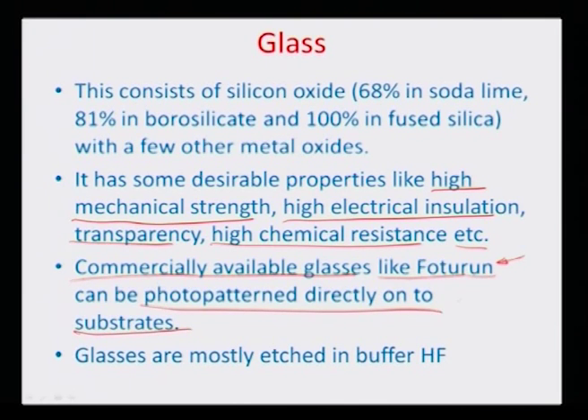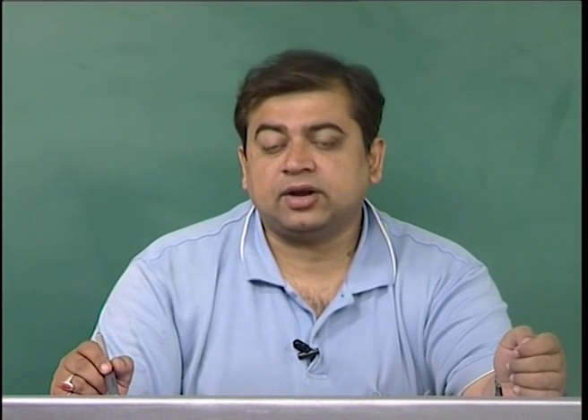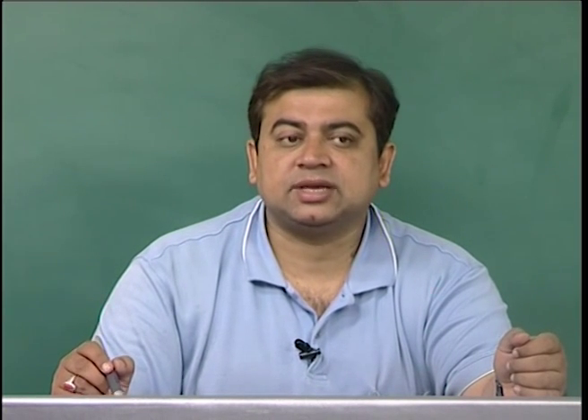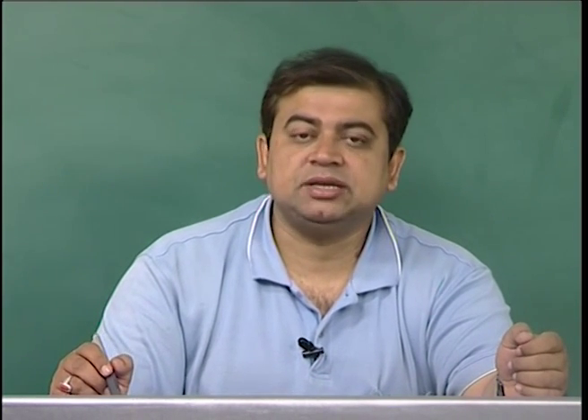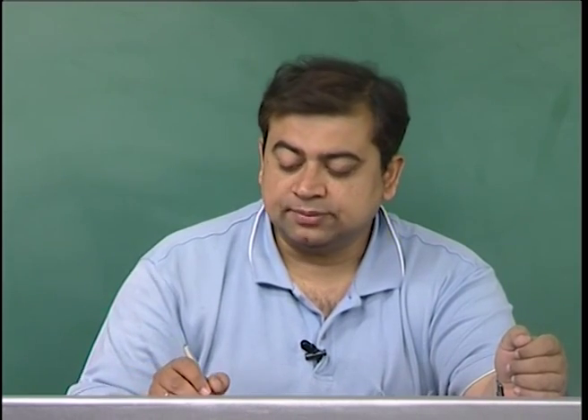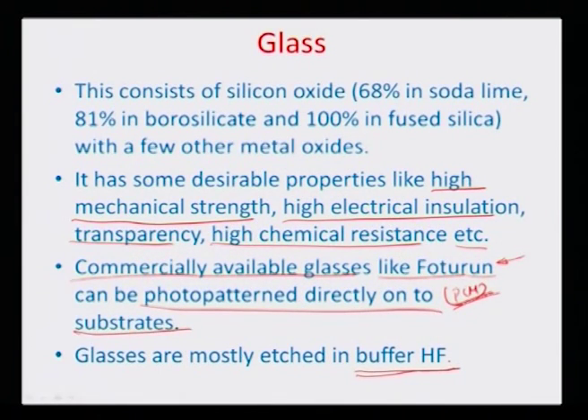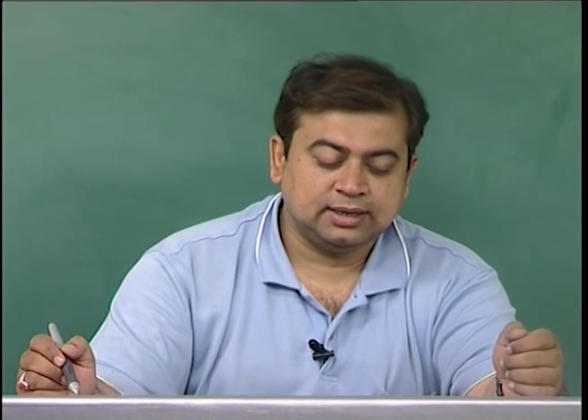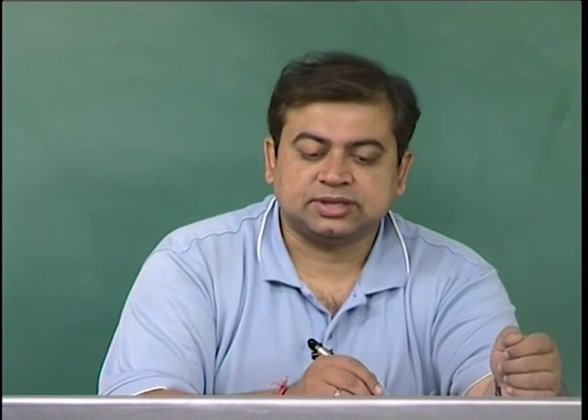And therefore, with glass also, you can actually use photochemical machining or PCM to result in a variety of features and structures at the microscopic length scale. So for etching glasses, for creating crevices, cavities, features, structures on the micro scale within such glasses, you normally use buffered HF solution, which is actually a solution of HF along with ammonium fluoride and water. So that's how glasses are important for the microstructure domains.